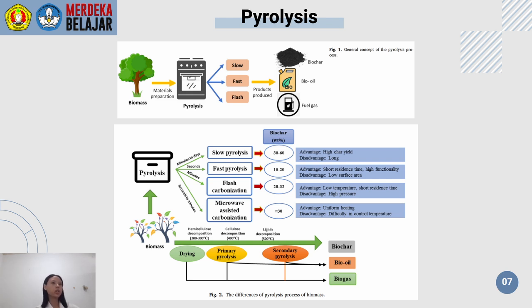The advantage of slow pyrolysis is high char yield, and the disadvantage is long time. For fast pyrolysis, the advantage is short residence time and high functionality, and the disadvantage is low surface area. For flash carbonization, the advantage is low temperature and short residence time, and the disadvantage is high pressure. For microwave assisted carbonization, the advantage is uniform heating, and the disadvantage is difficulty in controlling temperature.